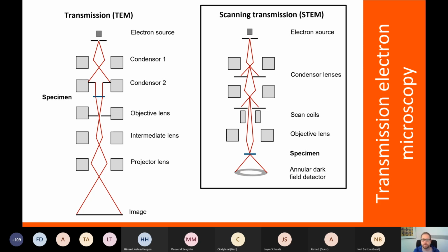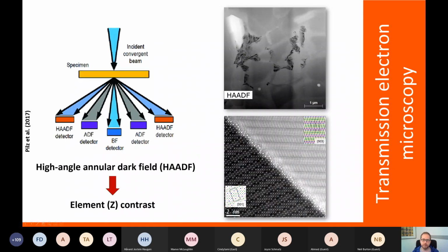Scanning transmission electron microscopy is quite powerful in the sense that it can provide us with additional information besides diffraction contrast or diffraction patterns. You can also get diffraction patterns using convergent beams. But the main thing I would like to highlight is you can get information of those electrons that are very highly scattered below the sample, something called high angle annular dark field. Simply speaking, this is similar to backscattered electron imaging inside an SEM, where these scattered electrons provide us elemental Z contrast information.